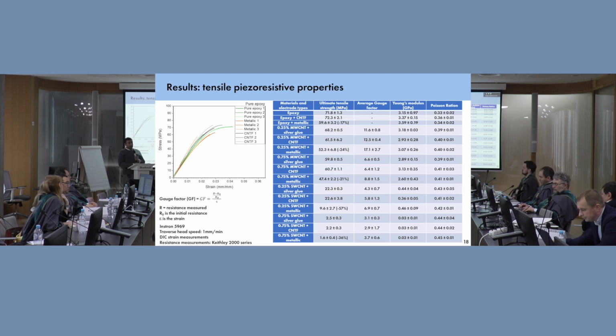So we took our samples, which were molded according to ISO 527, and we tensile tested them. During tensile testing, we conducted simultaneous electrical measurements using our Keithley 2000 series DMM. We used a transverse head speed of 1 millimeter per minute. Again, one of the reviewers corrected me on this. I thank them for it. And we calculated a gauge factor. A gauge factor is basically the sensitivity of your material to a stimulus. In this case, it is tensile strain.